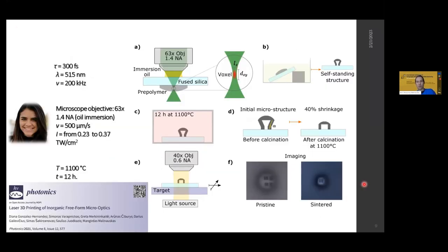Okay, so let's move to what we can do with it. And work done by Diana as a Europhotonics student at that time in our university. So applying it for microoptics, we need to optimize the shape to induce some precompensation, like sacrificial structures or support structures, which after annealing will bend, but that do not limit the shrinkage of our designed component. And eventually we can result in a shrunk, about 40% optical device, which as pristine, so sintered, can perform all kinds of optical functions like imaging, magnification, be highly transparent and suitable for optical applications.